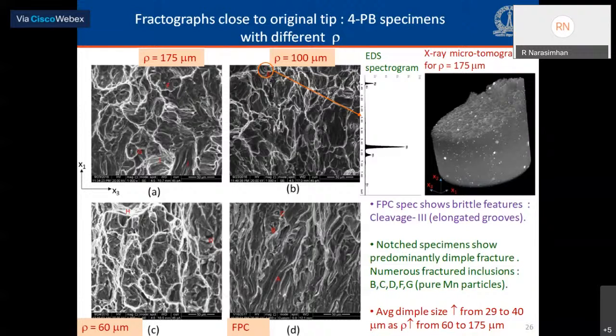On the other hand, if you look at all the pre-notched specimens, you would notice that there is dimple fracture, and some of these dimples actually have inclusions sitting inside them. We can see that more clearly from the X-ray microtomograph image on the right side, which shows dimple fracture on the specimen surface and numerous gray or white colored dots, which are actually second phase particles. Some of these have triggered the void growth, as we can see in the SEM fractographs. We also did an EDS spectrogram of some of these particles and found that these are mostly manganese-rich particles.